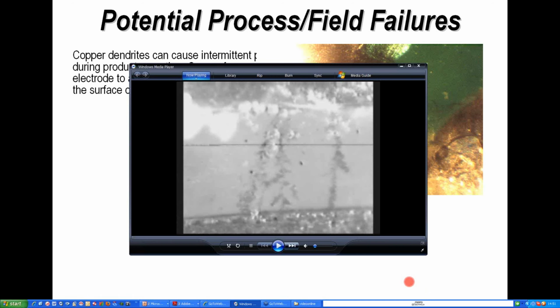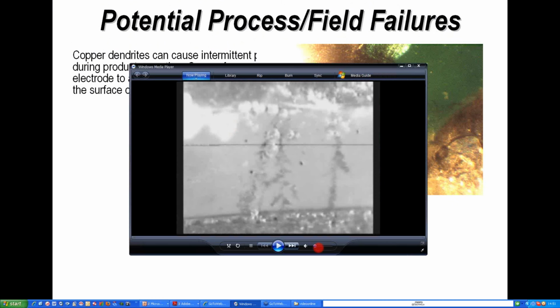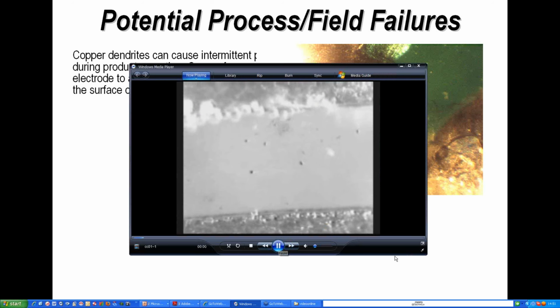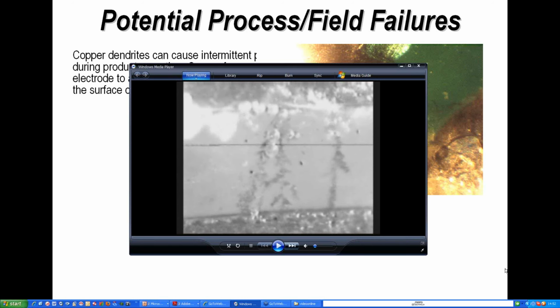If we just jump to a video clip, we should be able to see this in real time. The video clip illustrates the dendrite formation. What I'm showing you here is dendrites forming between two conductors on a printed circuit board assembly. And this is in real time. However, because there is quite a large droplet of moisture on the surface of the printed circuit board, this is the reason that it's happening quite quickly. In a normal situation, this may take weeks or even months to actually form.